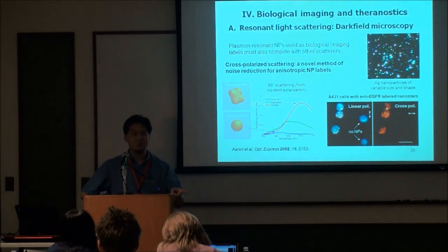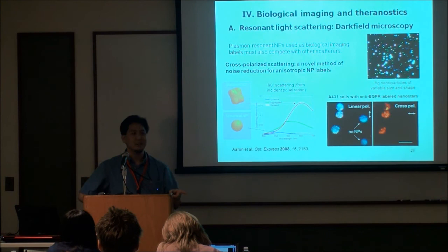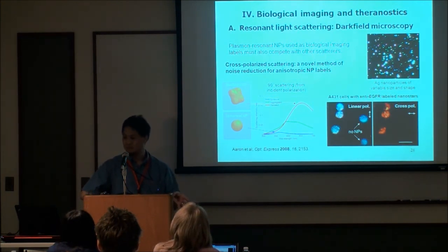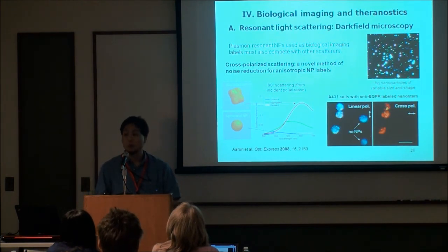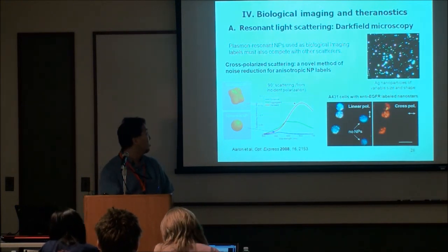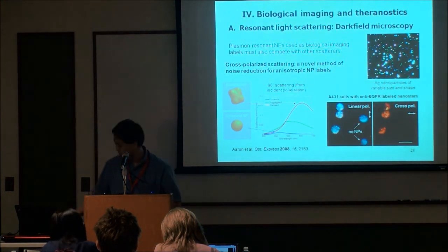It's one thing I forgot to mention throughout the course of this tutorial, and that is that if you're going to develop a contrast agent for biological imaging, you don't want particles that are too big. Okay, so working with particles that are much above 100 nanometers gives rise to all sorts of problems. In a biological system, you'll have problems with clearance, for example. But it's also hard to stabilize particles that are much above 100 nanometers, okay? And with the optical properties, you don't gain that much more just by changing the size. So really the issue here is to change the finer shape of the particle to be able to pull out wavelengths of interest and also properties such as this depolarization.